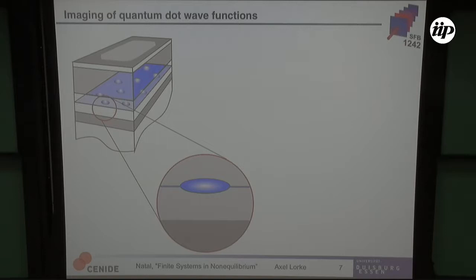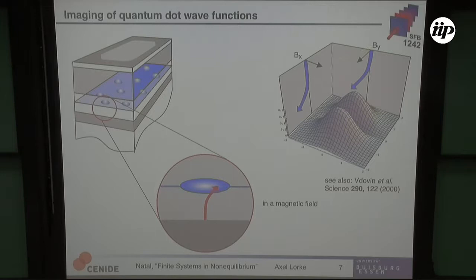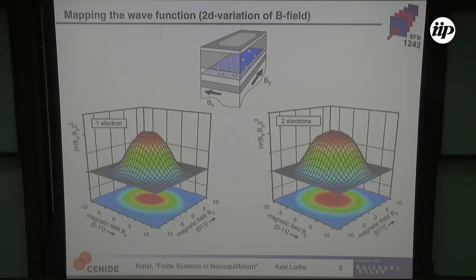Here is a very, very cartoon-like representation. We have the back contact, we have the quantum dot layer, we have the tunneling, and of course, if you apply a magnetic field, you will, so to speak, displace the tunneling current. And you can do that now in the different directions. And depending on how large the wave function will be at this point or at this point, you get a higher or a lower tunneling current, and you can map out the quantum states in these quantum dots as they are filled with one electron or two electrons. That's just the S state, so you get just a Gaussian wave function, more or less.